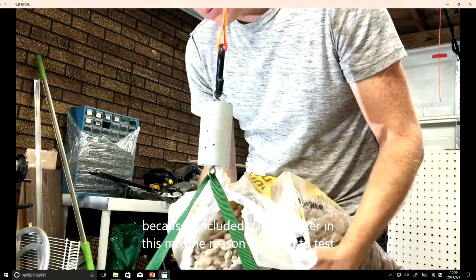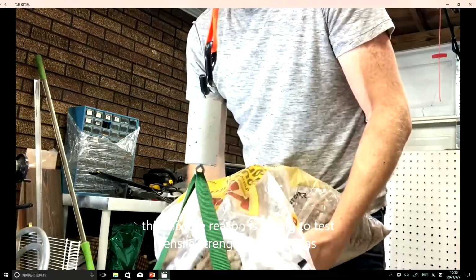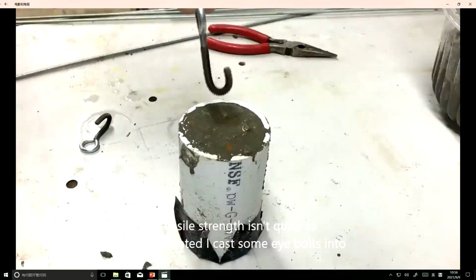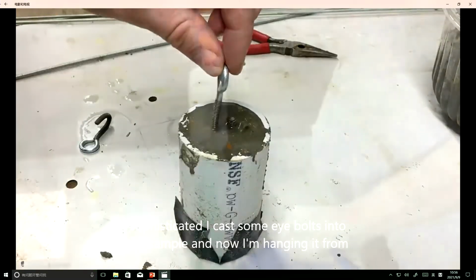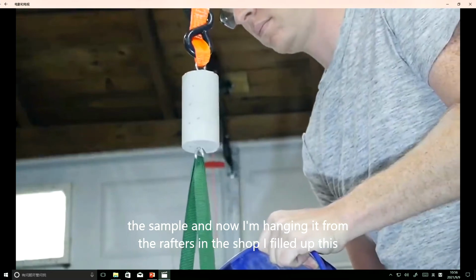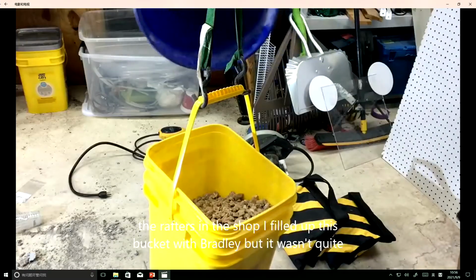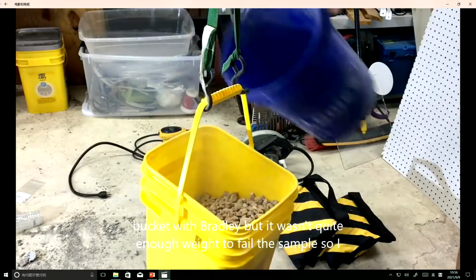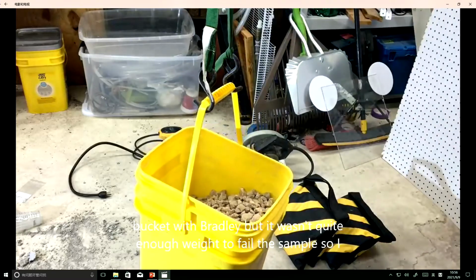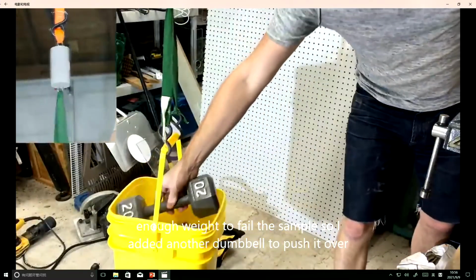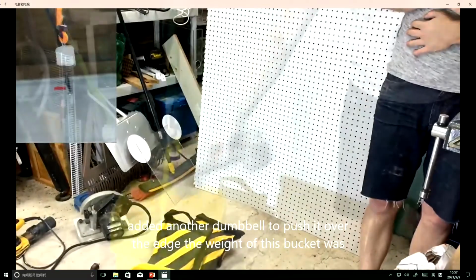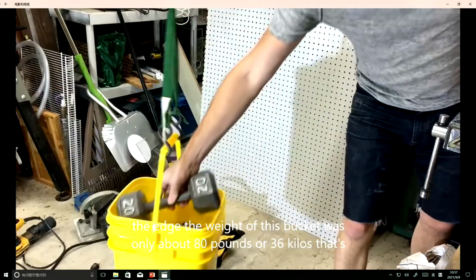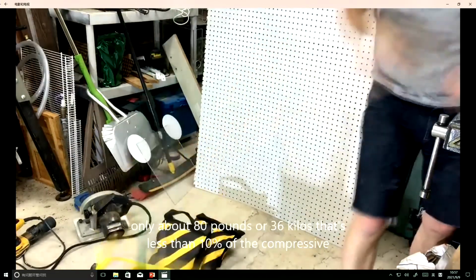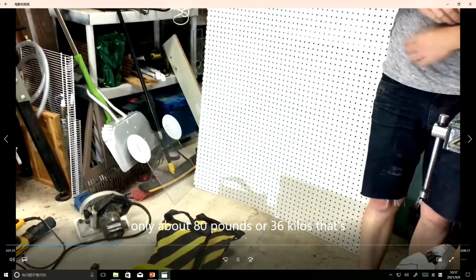But for concrete, that's pretty low because I included a lot of water in this mix. The reason is my rig to test tensile strength isn't quite as sophisticated. I cast some eye bolts into the sample, and now I'm hanging it from the rafters in the shop. I filled up this bucket with gravel, but it wasn't quite enough weight to fail the sample, so I added another dumbbell to push it over the edge. The weight of this bucket was only about 80 pounds, or 36 kilos. That's less than 10% of the compressive strength.